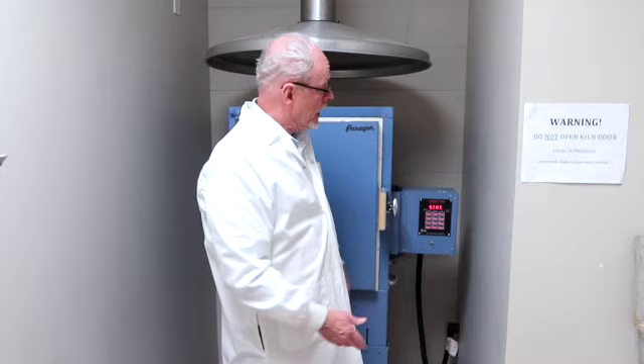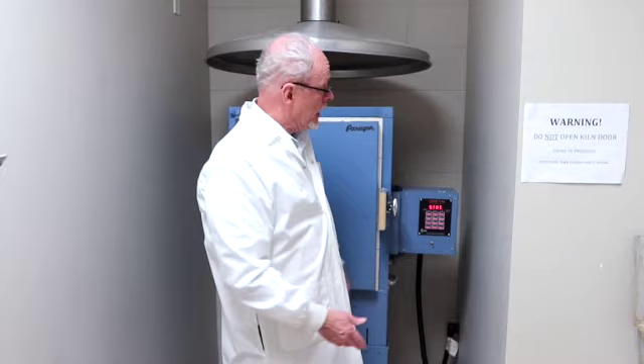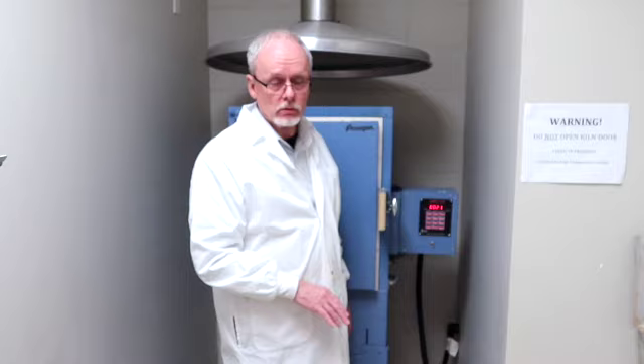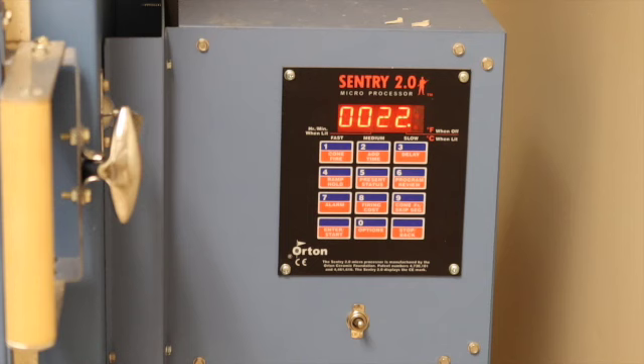Okay it's now started on the program that I preset and it will rise to that temperature, you can hear the kiln starting to operate now. It will rise to that temperature which I think was set for 500 degrees and hold it at that temperature for I think two hours before it reduces to room temperature again so we'll have to come back later.